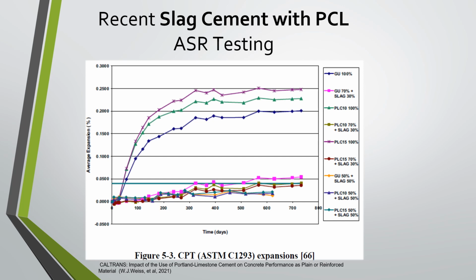And you can see here that if we're using general use cement, which would be type 1, or if we're using it with the PLC, we're still seeing those same effects. Slag cement, as we can see here, is going to greatly improve the ASR abilities on it so that we're mitigating for ASR. So in these aspects, that's where we want to use those SCMs like slag to help improve that concrete, right? That's going to make it more durable, last longer.